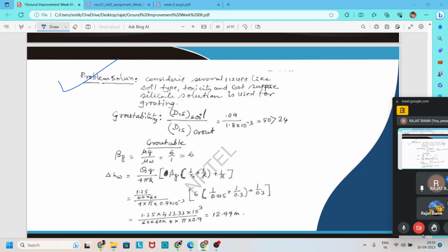So first we find out the groutability ratio, to see whether it is suitable for grouting or not. The groutability ratio is the D15 of soil divided by the D85 of the grout. By putting all the values, we find that the groutability ratio comes to about 50. And we know that for soil, when we apply soil cement, the groutability should be greater than 24. And here it comes about 50, which is also greater than 24. So the soil is groutable.